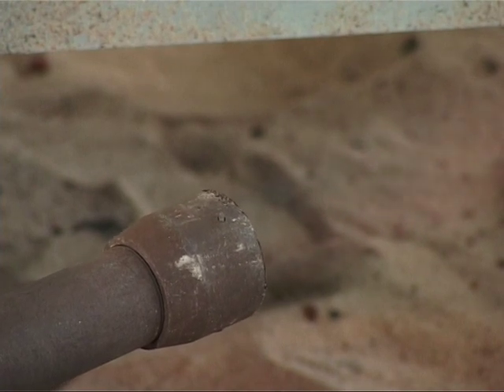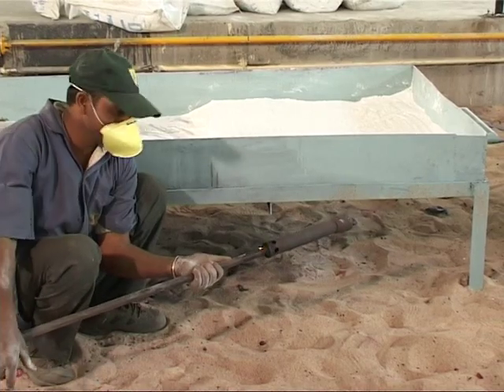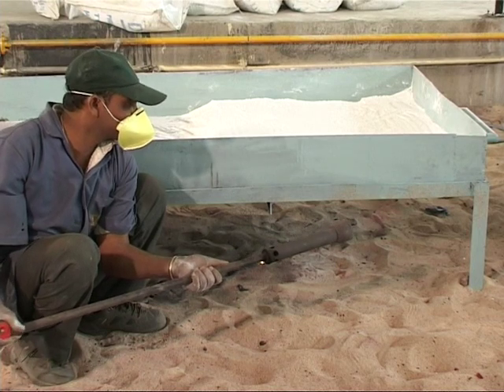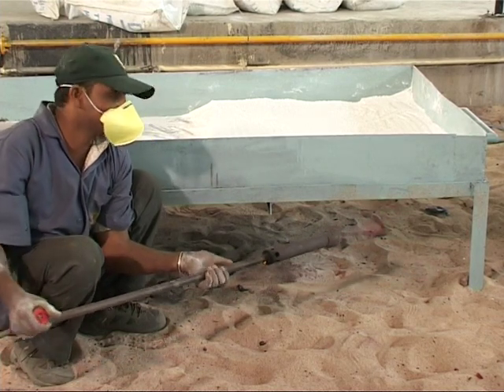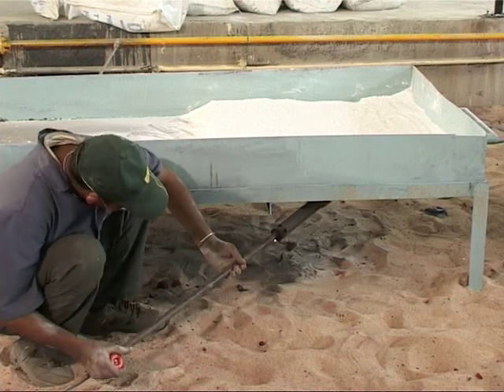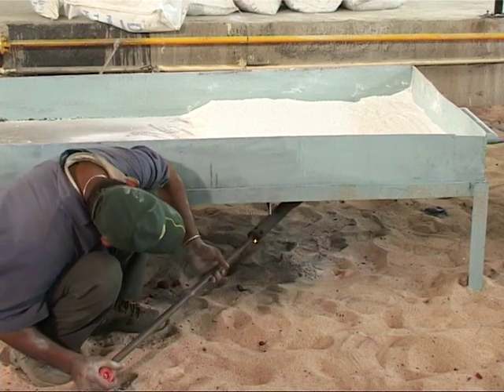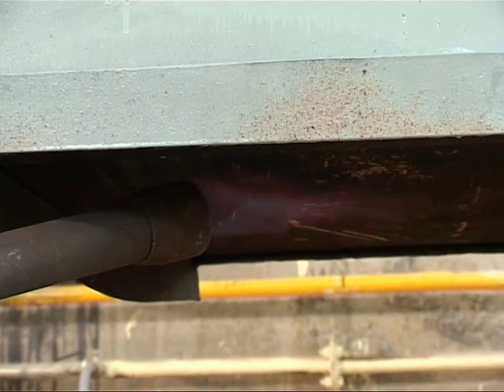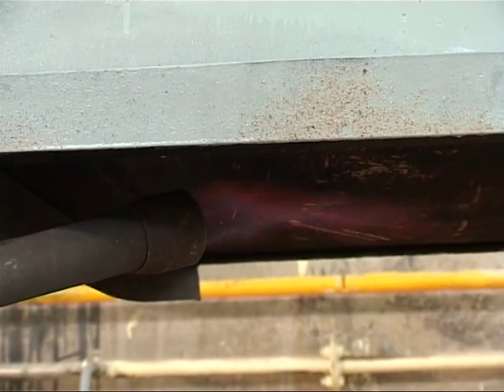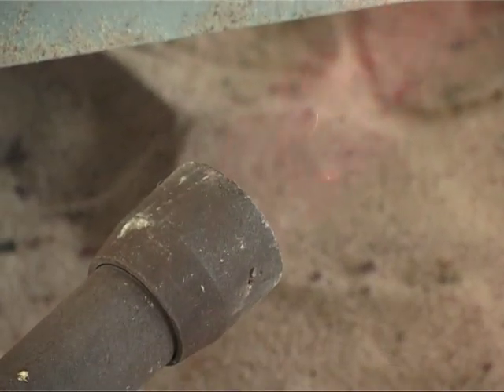Use separate trays for heating and drying and for mixing. Heat the drying tray with gas if possible and available. When using oil burners or charcoal and firewood, beware of spillages that can contaminate the ramming mass, bags or containers. Aim for drying temperatures of 70 degrees centigrade if binder is premixed. Otherwise, 100 degrees centigrade or so.